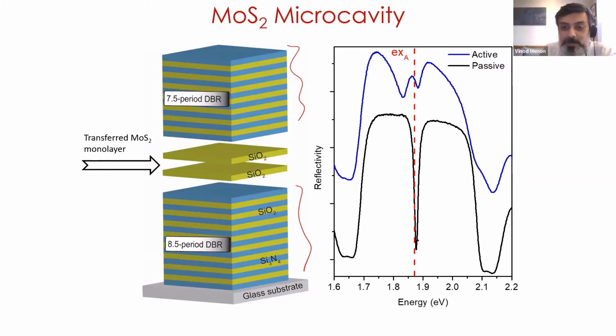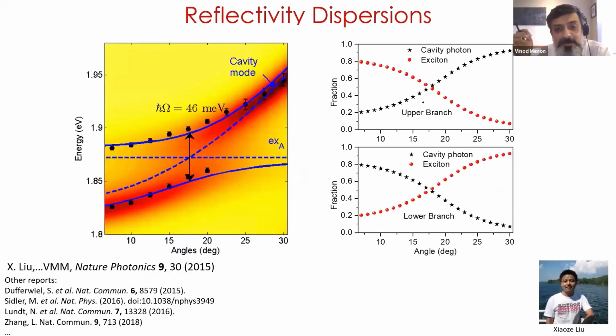And what you see here is what happens when you go away from this. So you have a flake sitting somewhere here, and then you go to a region that is here, and what you see is that it's just a cavity resonance. And then you go to this region and you get this splitting, or the Rabi splitting that I was just telling you earlier about, and you get this strong coupling. In fact, if you look at this slide here, you will see that you get the typical anti-crossing behavior, and you can extract out the Hopfield coefficients and so on.